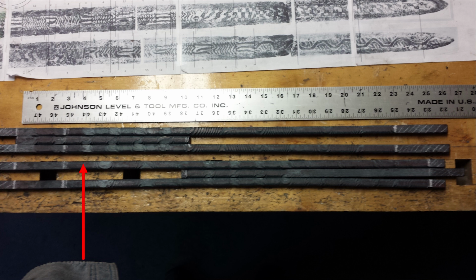The 4th bar started with the short checkers pattern and continued to the chevron straight section before the serpent. It finished with the continuous chevron which underlines the serpent. The other half of the 5th bar is inserted here to form the central bar of the chevron straight first, and finishes on a single straight laminate which would become the serpent. The 6th bar was a repeat of the 4th one and completed the pattern on the serpent side.